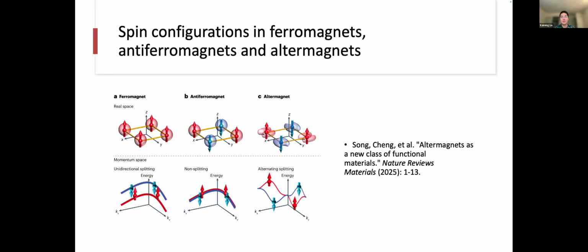In altermagnet, spins are antiparallel, so it doesn't have a net magnetic moment either. However, the sublattices are connected not by inversion or translation symmetry, but by rotation symmetry. So in momentum space, the energy band has alternating spin splitting.